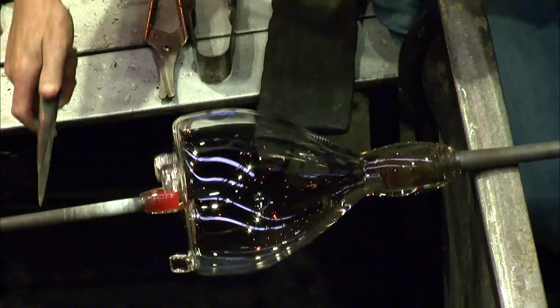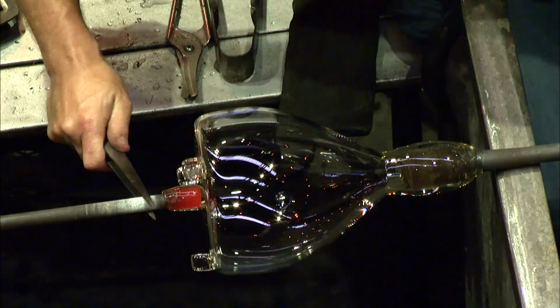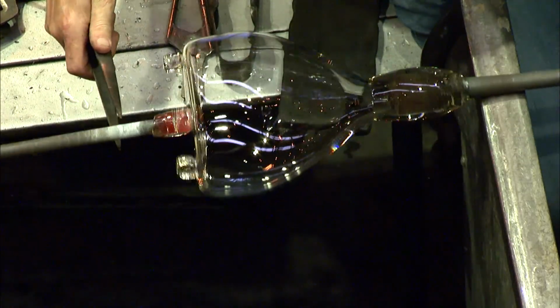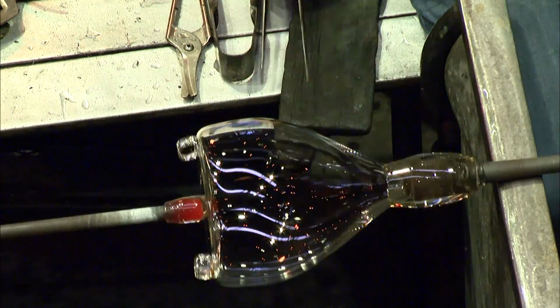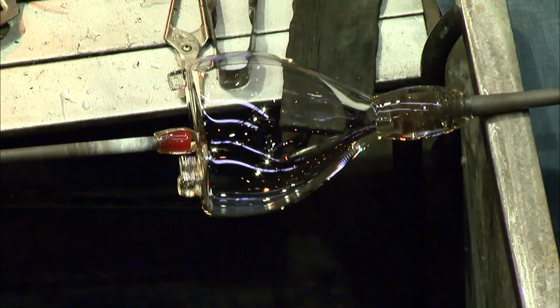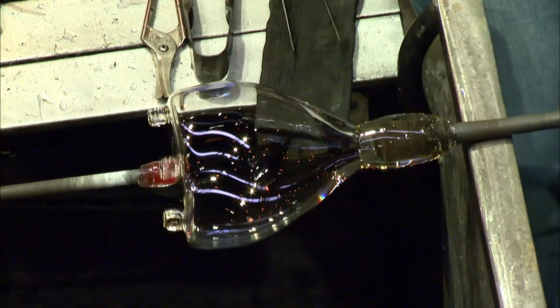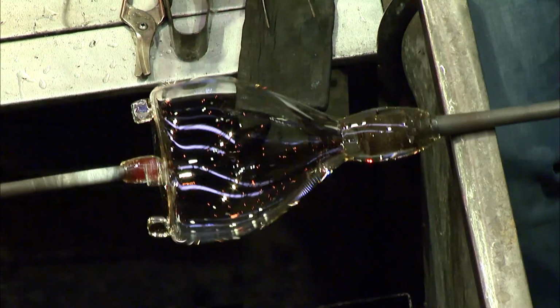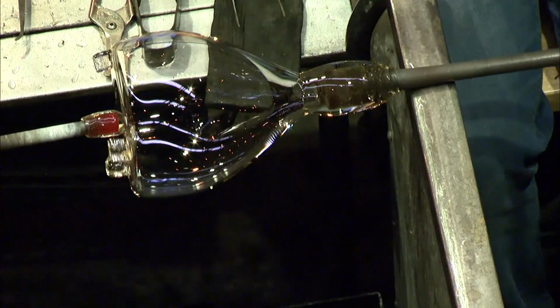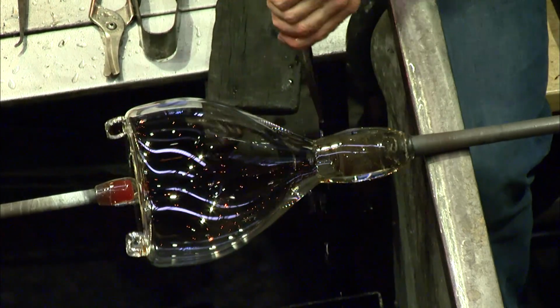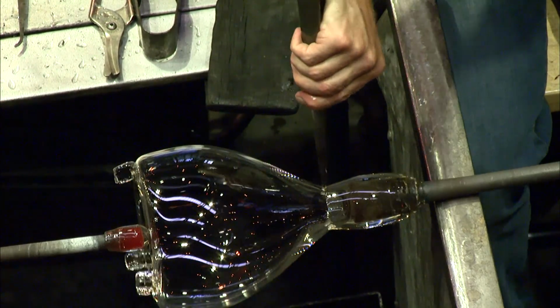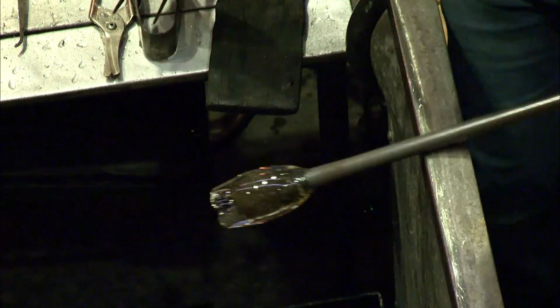The constriction line right off the end of the pipe that Eric created, that part of the piece needs to be cold enough that we can create thermal shock in our glass to break it free. And we'll be able to do this with a drop of water or maybe just cold contact from one of our hand tools. The type of glass that we work with is vulnerable to cracking and breaking due to this drastic temperature change around about 1,000 degrees Fahrenheit. So setting it up just right, applying that drop of water to send the temperature downward, and a leg tap to the iron, we can break the piece free.